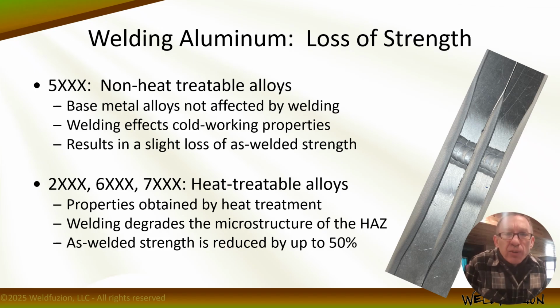So expect welds on these materials to see about a 50% reduction in strength post-weld and still meet code requirements. For example, the tensile strength of unwelded 6061-T6 is approximately 42 to 45,000 psi, and the AWS D1.2 structural welding code for aluminum publishes the as-welded requirement of tensile strength in order to meet code at 24,000 psi. That's a little less than a 50% reduction compared to the unwelded base metal. Why? Because even with proper filler metal selection, the heat of arc welding reverses heat treatment properties. Think of it as over-annealing the base metal. Then excessive heat input can further reduce strength and increase the width of the heat affected zone. Right? So heat is bad for these alloys.